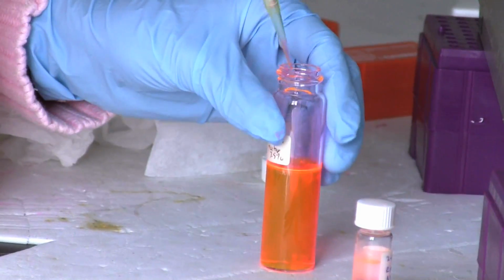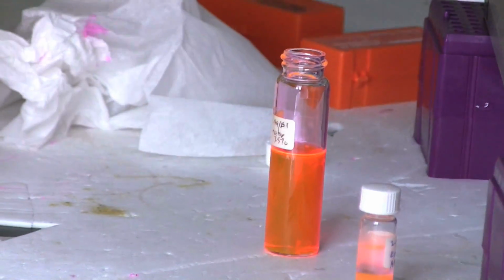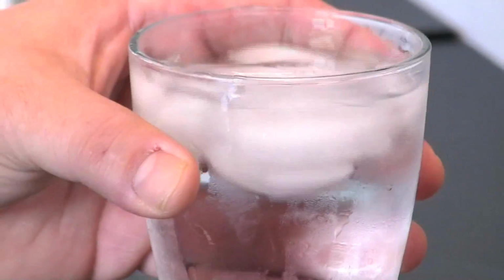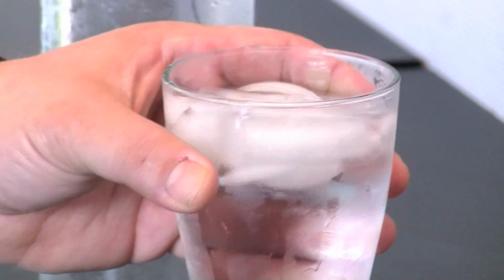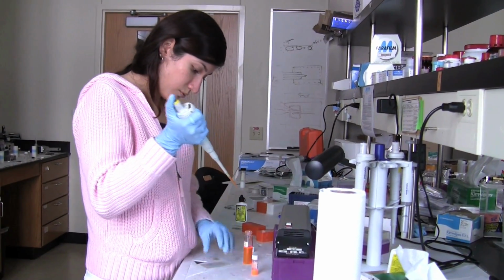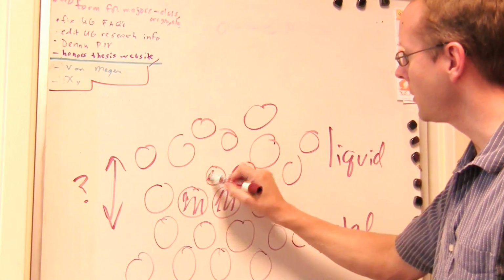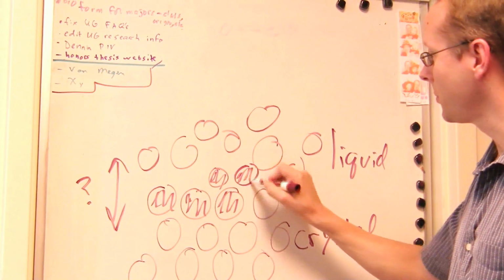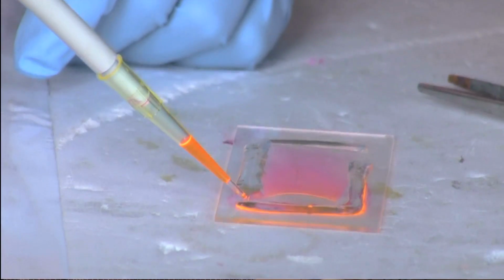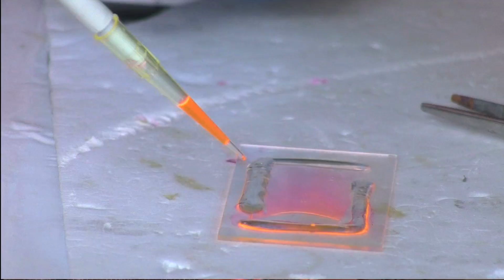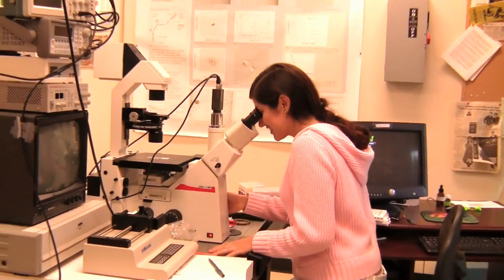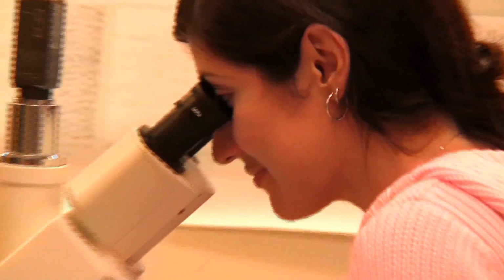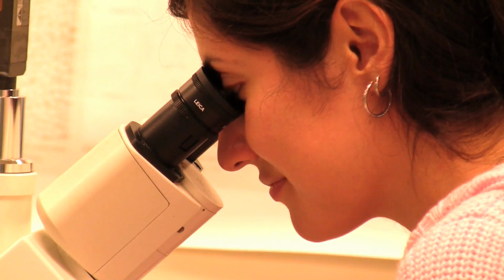What we did was an experiment with small plastic particles in a liquid, and the particles themselves are analogous to the molecules in the water. And they can form into crystalline arrays where they form hexagonal layers, or they can form into liquid-like disordered structures. And we made a system where the two of them were put together. So we had a boundary between a liquid phase and a crystalline phase, but we could see that with the microscope. So the experiment that we did was to look at this interface between the liquid and the crystal and see how it looked over time.